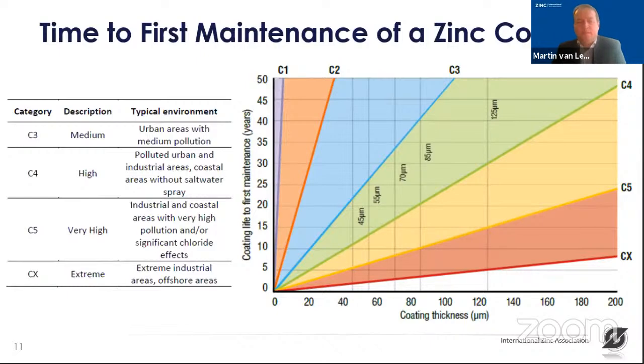If you depict these different environments in a plot of zinc coating thickness versus coating lifetime to first maintenance, you can see how long your zinc coating will last until first maintenance is required on your steel substrate. Take, for example, an 85 micrometer thick galvanizing coating in a C3 environment. The time to first maintenance will be somewhere between 21 and 42 years.